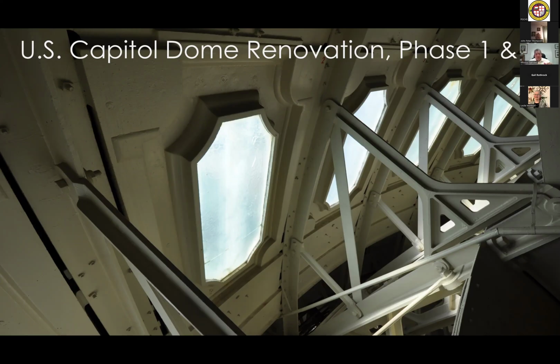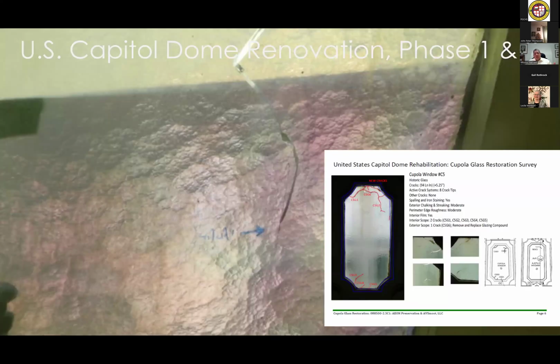These are the cupola level windows. Over time, though, these have developed all kinds of cracks, and you can see here's some of these cracks. On the bottom right, you see the drawing that we were presented with when we bid on the project. Every crack was mapped out in terms of its length. And so we scoped that out, and then we did our own survey and determined that the cracks were continuing to grow.